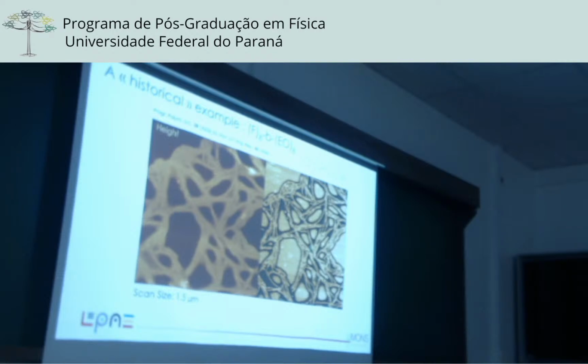This is the topography, this is the phase telling you about the mechanical properties. And if you measure the width of these fibrils, they're about 10 nanometers. Which means that we have conductive or semiconductive wires of 10 nanometers. You can start to play and use those nanowires for applications.